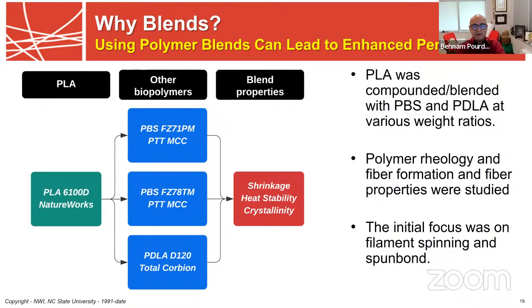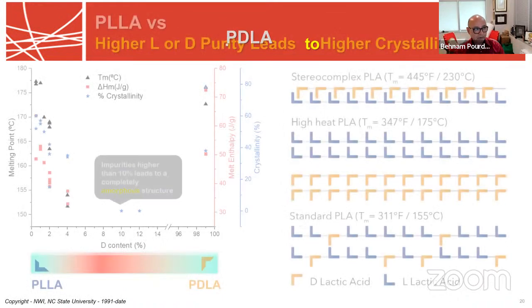PLA has a very, very low crystallization rate, which creates many challenges. Its total crystallinity is low, its glass transition is low, its heat deflection is low. And so the intent was to really see if we can improve these by just using polymer blends. And of course, the polymer rheology and the immiscibility of these materials would make a challenge in terms of the filament spinning, but I'll share with you what we've done.